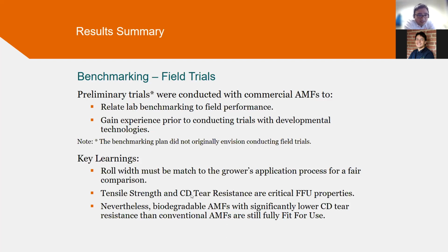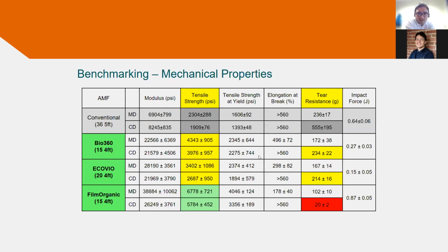The tensile strength and the cross-direction tear resistance proved to be critical fit-for-use properties. And although biodegradable films had significantly lower cross-direction tear resistance than the conventional, some of them were still fully fit for use. So let me show you what that means. This is the same data that we had before, but here we can focus on the tensile strength right here, and then the tear resistance.